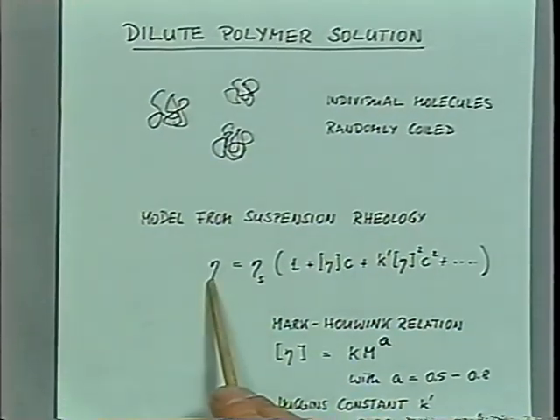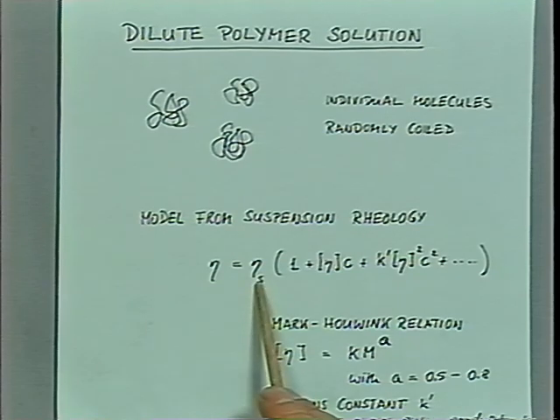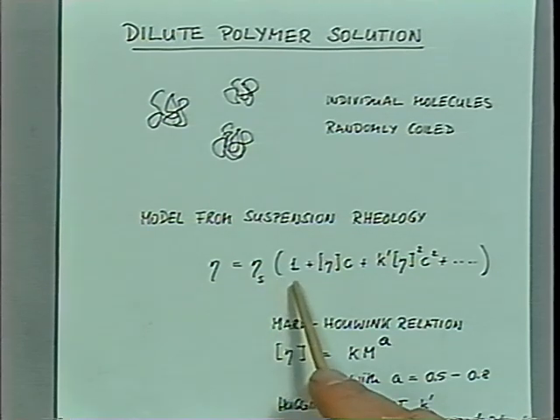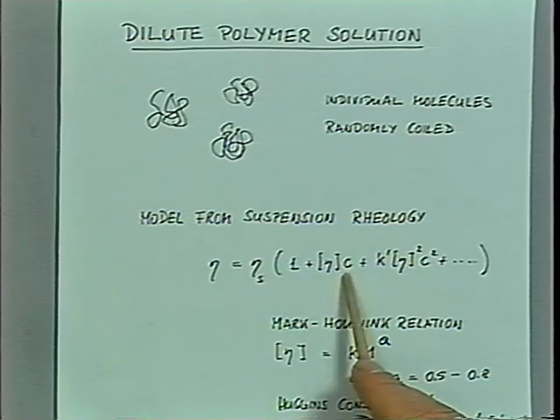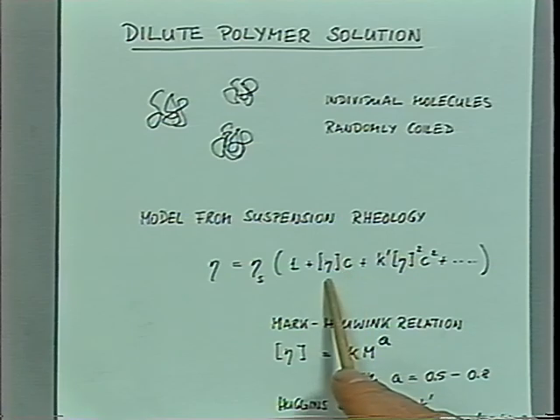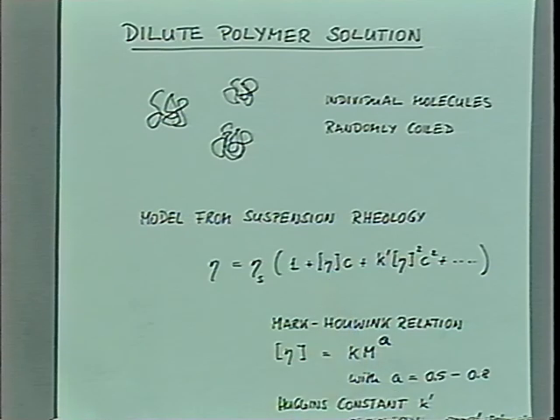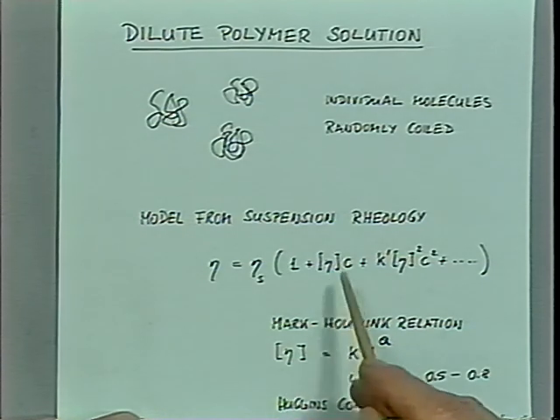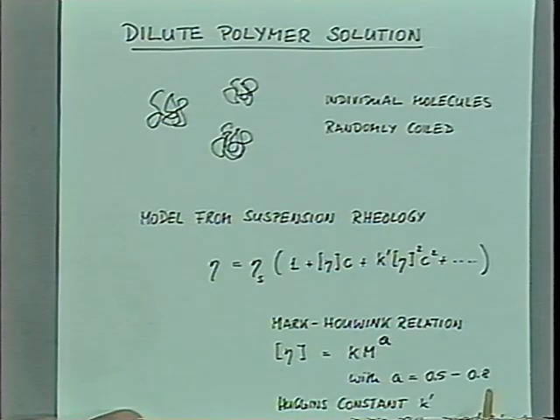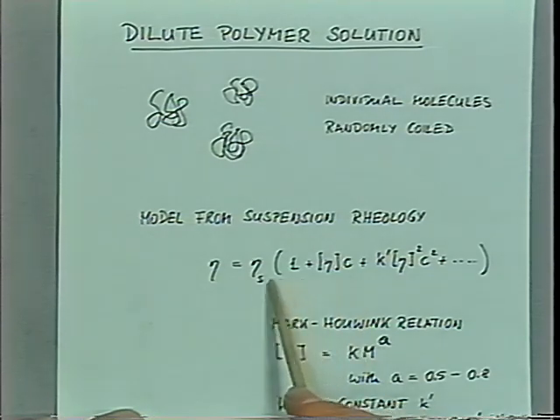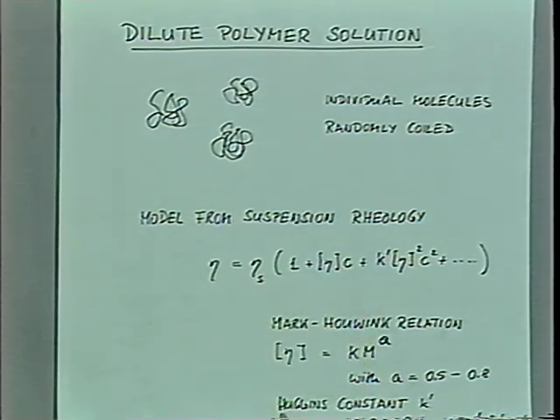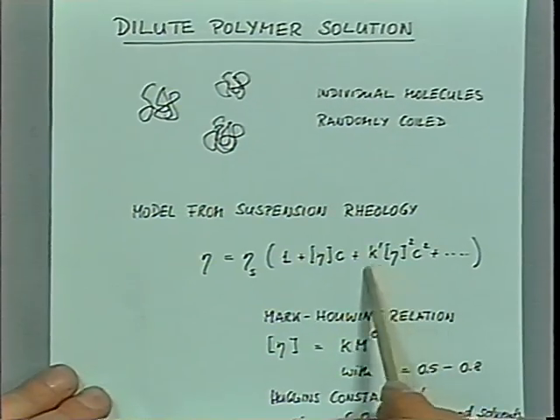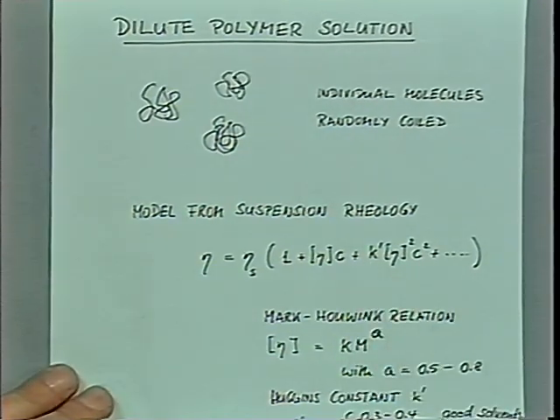The viscosity of the solution is equal to the viscosity of the solvent times 1 plus a coefficient here containing the concentration of polymeric material and the so-called intrinsic viscosity. Now, in Einstein's case, this would be 2.5 times the volume fraction of solid filler. If you want to extend this Einstein formula to larger molecules, to larger concentrations, then pretty soon a nonlinear term comes in and you can modify that.